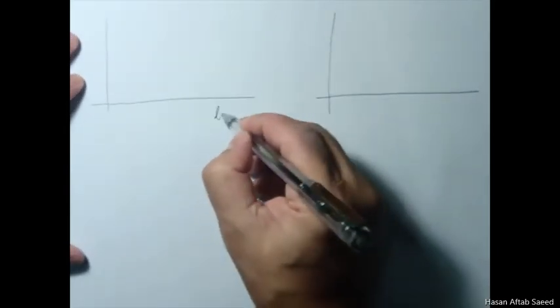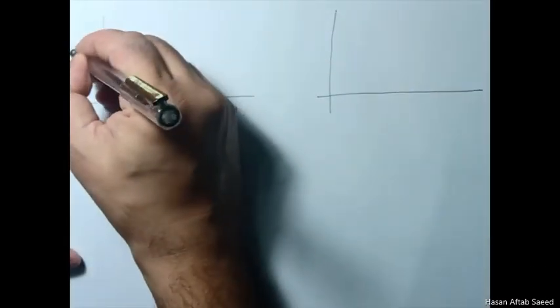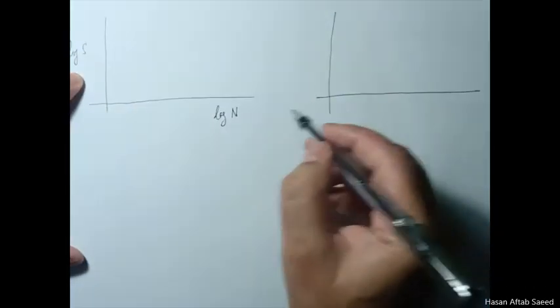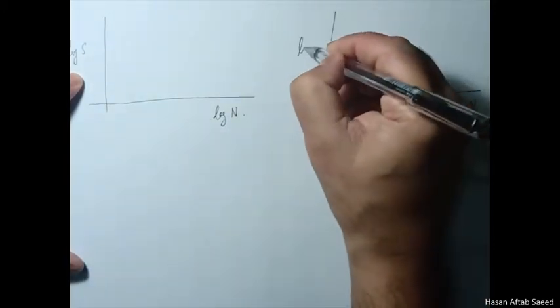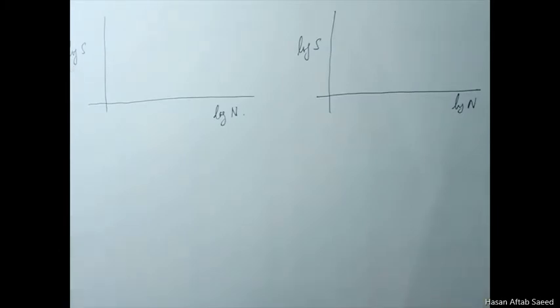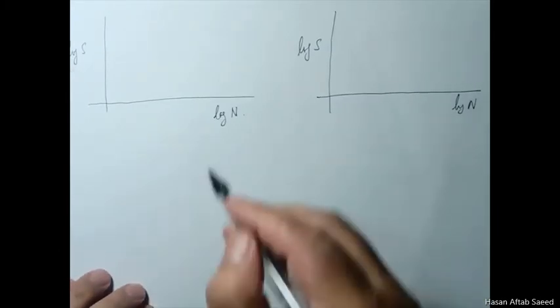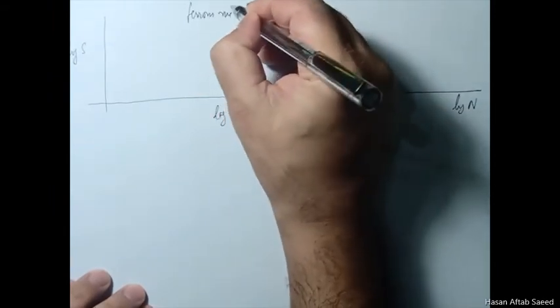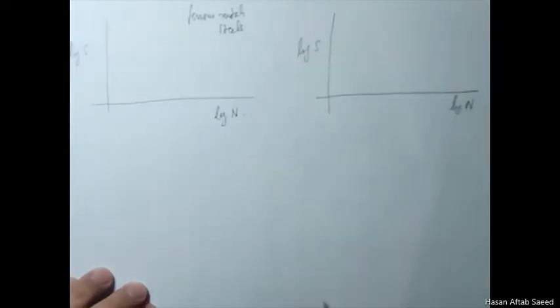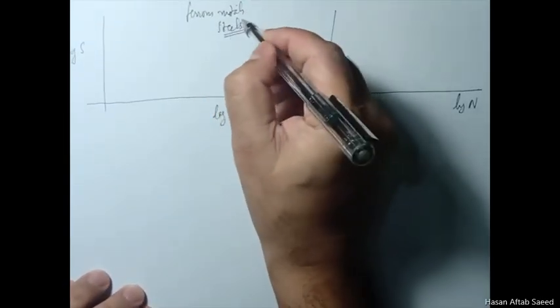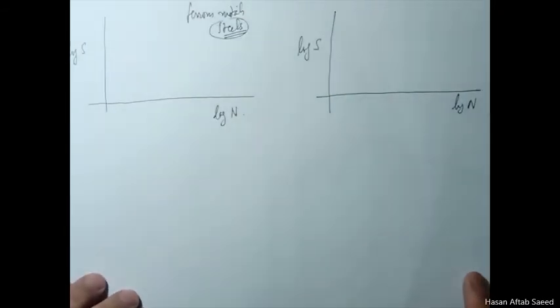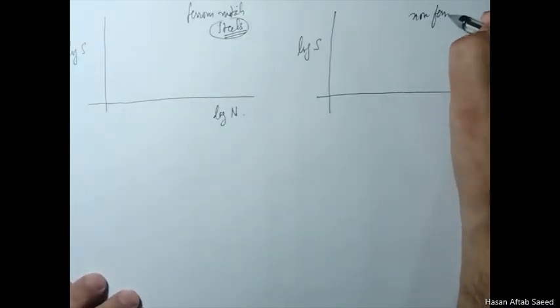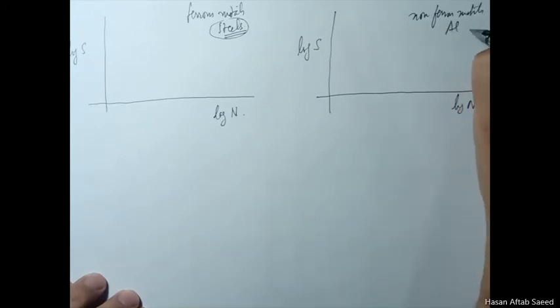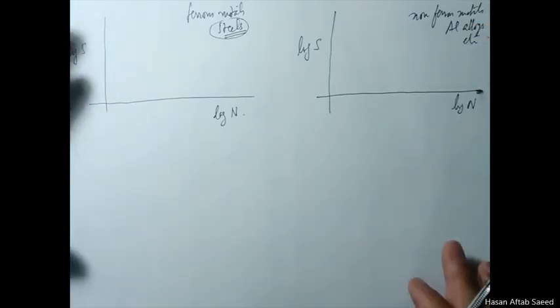But if we... this is the log of stress levels, and this is log of the number of revolutions. This tells us a very neat story. For one kind of material, and that is ferrous metals and steels, for example, because they are so predominantly used. So even if this is only for steels, it is very important for us. And for non-ferrous metals, for example, aluminum, alloys, etc., we get a somewhat different kind of a graph.